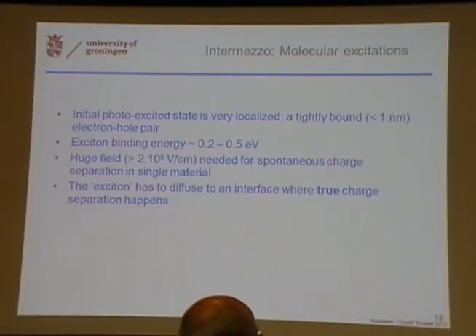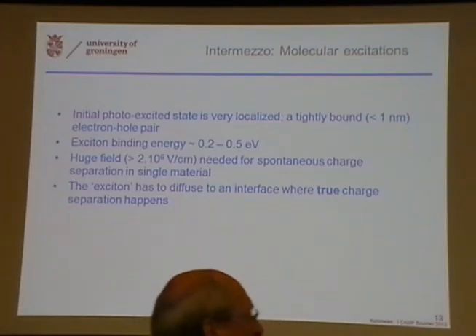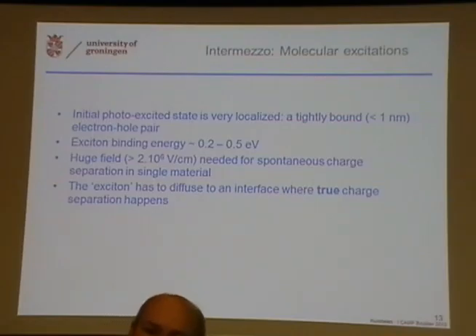Okay, we have an exciton binding energy of roughly 0.2 to 0.5 eV, and you would therefore need a huge field to pull those two apart.